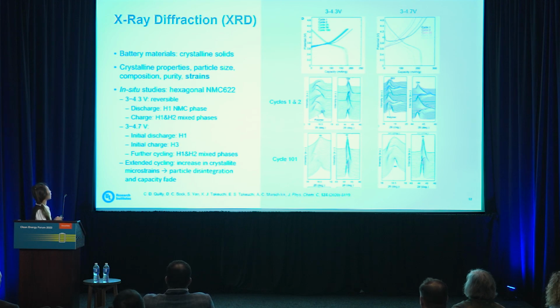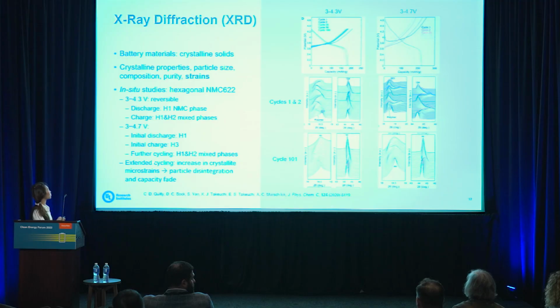However, when we're looking at a wider voltage window, the authors found that it starts with an H1 phase, but it goes into an H3 phase with additional cycling to higher voltages. And with further cycling, it actually goes back to what we see for the lower voltage window, so it goes into H1, H2 mixed phases. So XRD is a good tool for us to see what's happening with our active material. The authors also found that with extended cycling, there is an increase in crystalline microstrains. This is something that you can see when doing some Rietveld refinements, and this is linked to particle disintegration and capacity fade.